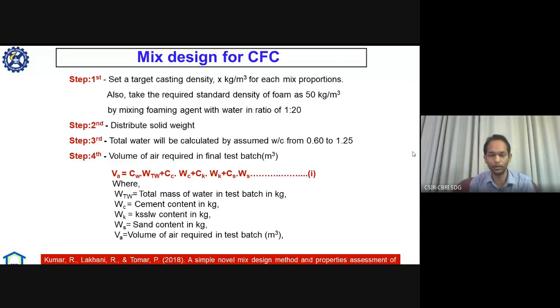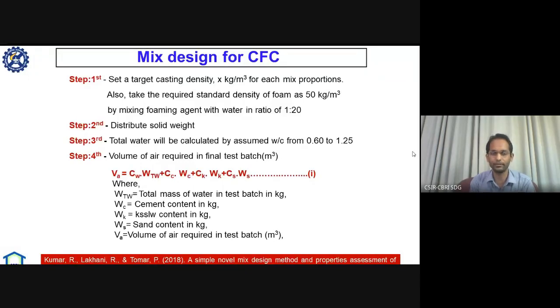You can't go below that, because if you develop a foam with a foam density of 20 kg per meter cube, it will have less foam stability, and it will collapse with time before the setting of cement. More specifically, before the initial setting of cement, which is 30 minutes, as you all are aware, the specification for OPC 43 grade, which is given in IS 8112. So for our case, we have taken the foam density of 50 kg per meter cube, and for developing this, we have done the trial by mixing foaming agent and water in the ratio of 1:20, 1:30, and 1:50.